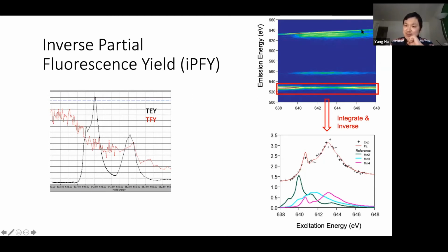And on the 2D map here, we see the manganese L3 RIXS, and this band is the manganese core transition. And this part is actually the oxygen emission. And notice we are sitting at 640 eV, which is about 100 eV above the oxygen edge. So in theory, the oxygen tail is supposed to be flat and contains no features.